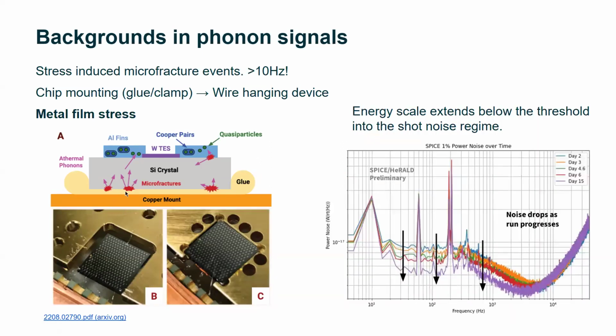And even without gluing and only with this wire hanging, you still have the stress between your metal films and the crystal. After you cool it down, the stress builds up. Since your deposition, the stress is built up, and then it releases. So it's an unavoidable problem. And more fundamentally, it not only shows up as individual pulses, but below your energy threshold, it shows up as shot noise. You can see your noise spectrum becomes better and better over a course of say 2 weeks.